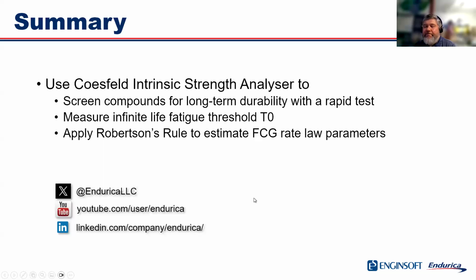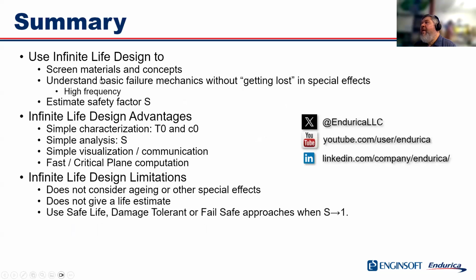All right, so I'll just summarize here and say that if you want to characterize this, you want to use the intrinsic strength test. It's a great screening test. If you're looking at long-term durability, it gives you the threshold T naught that, if you run it with the control material, you can use to plug into your simulations and get safety factor. And if you want, you can use Robertson's rule to quickly estimate a crack growth curve. The analysis that we've shown you is great for understanding basic failure mechanics without getting lost in all of the rubber's special material behavior, and it can give you a safety factor, which is good for doing A versus B comparisons, maybe in design.